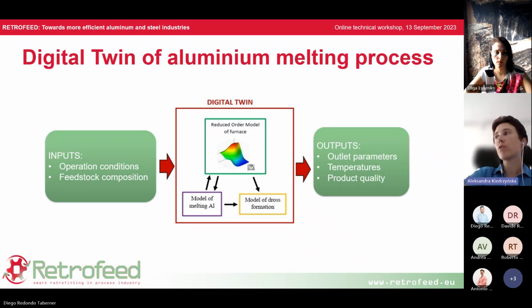Temperatures of refractory, source, and product quality, defined, for example, by amount of dross. In our case, the digital twin consists of 3 submodels: a reduced order model of the furnace, a model of aluminium melting, and a model of dross formation. Why did we have to split our digital twin into submodels?